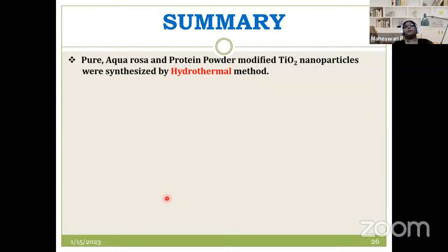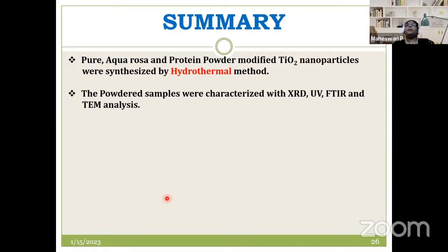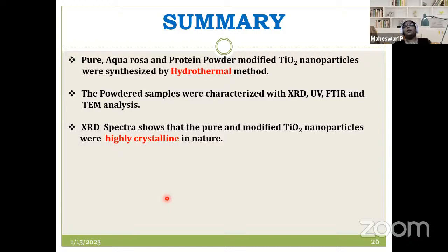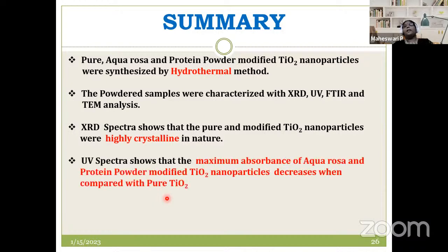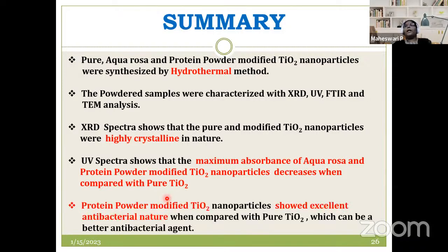From the summary, I can conclude that the synthesis has been done for pure, Aquarosa modified and protein powder modified titanium dioxide nanoparticles. The powdered samples were subjected to characterization using XRD, UV, FTIR, and TEM analysis. The XRD spectra show that the pure and the modified samples are highly crystalline in nature. In the UV spectra, we can see the absorbance decreased with the addition of the modifiers. On the whole, the conclusion is that the protein powder modified titanium dioxide nanoparticles act as an excellent antibacterial agent when compared with the pure titanium dioxide nanoparticles.